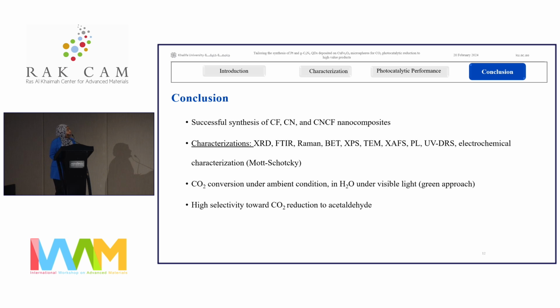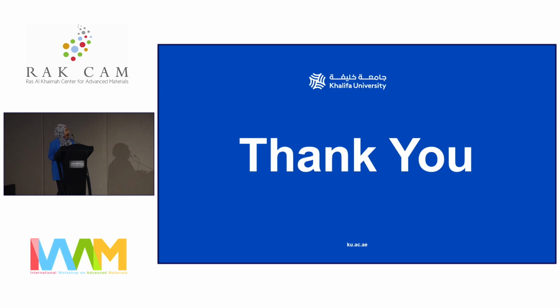So in conclusion, we successfully prepared different nanocomposites, characterized them using different techniques, and tested the CO2 conversion using these nanocomposites. We observed that under ambient conditions and using water and visible light irradiation, we observed the formation of acetaldehyde, and the catalyst was highly selective toward forming acetaldehyde.